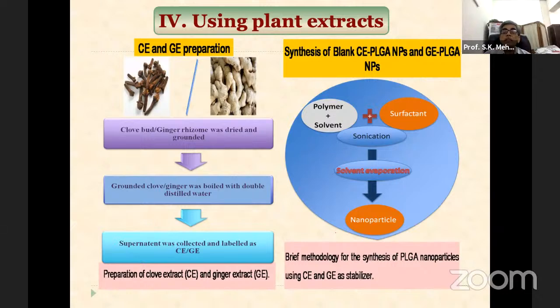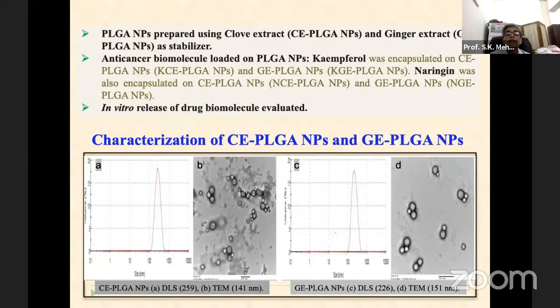So you have to first characterize this, what are the components available, and the procedure is sonication, solvent evaporation, and finally you get the nanoparticle if you are using polymer plus solvent plus surfactant. So this procedure one can easily use, but the main thing is that you can use various drug molecules, biomolecules, and you can incorporate them in these clove extracts or ginger extracts, and this PLGA nanoparticle which we are preparing from CE and GE nanoparticles, and you can use anti-cancer biomolecules loaded on these PLGA particles, because PLGA particles have been the most accepted ones for use in the body.